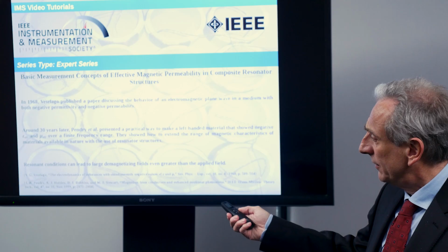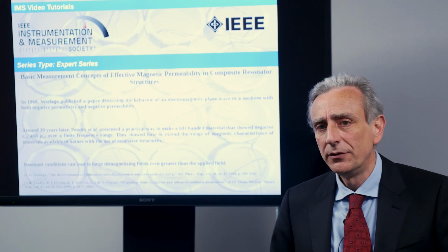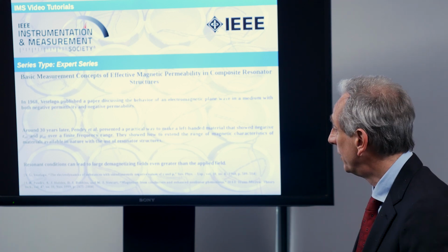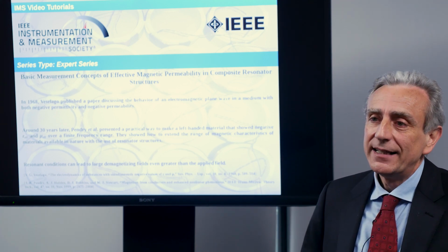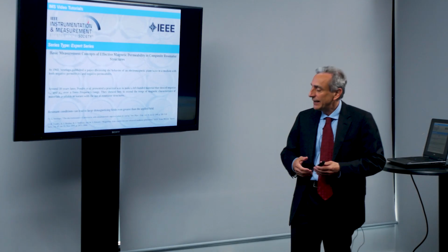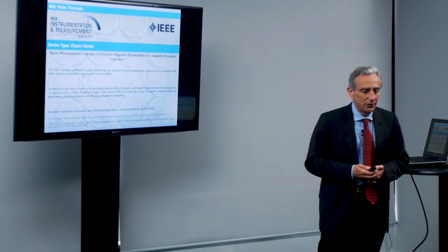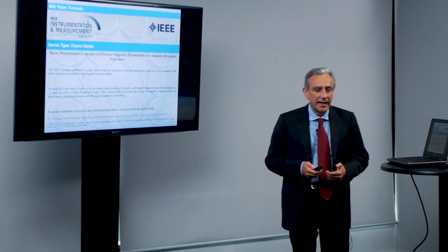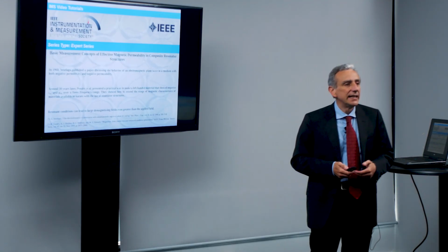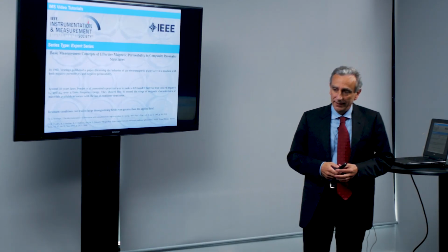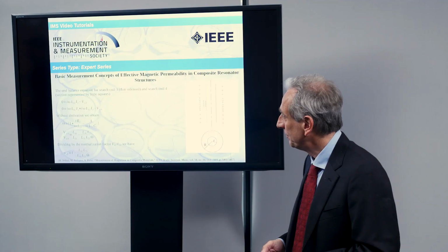The fact is, due to resonant condition, that the magnetizing field, the stray field, could be even greater than the applied field, and this could open the possibility to have unusual magnetic behavior, and in our case, to have at the end a negative value of the magnetic permeability.